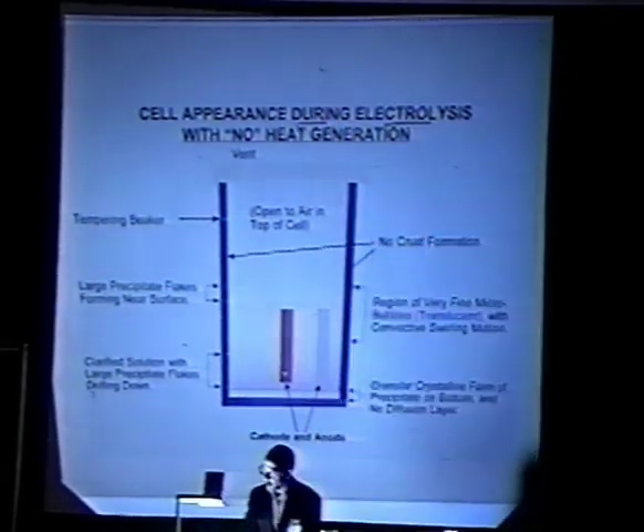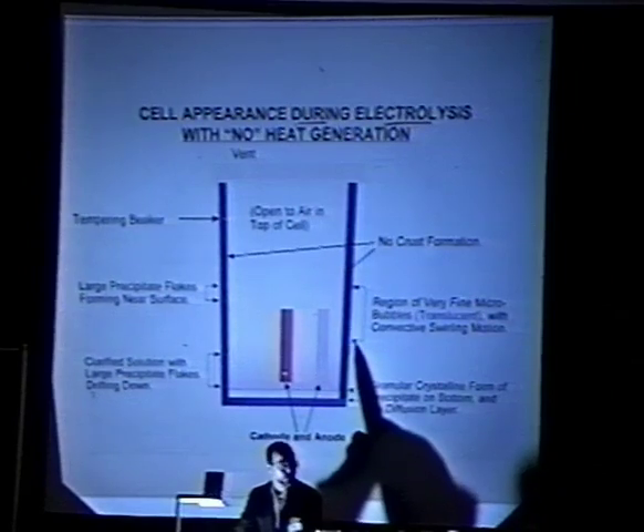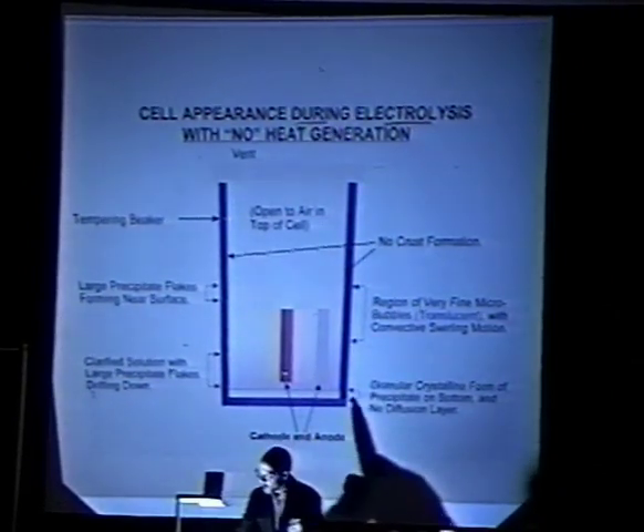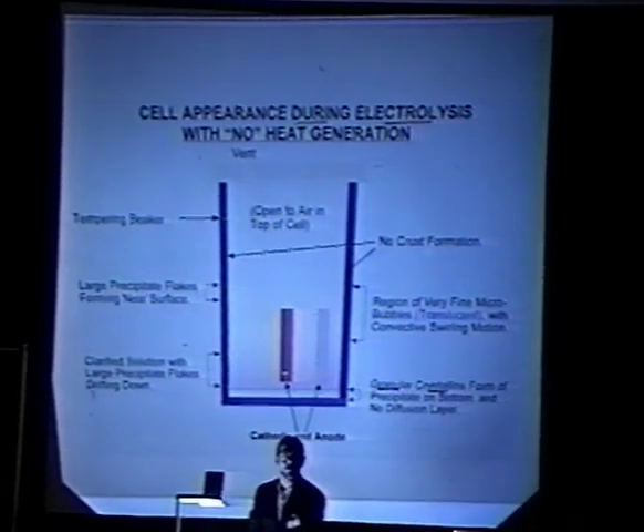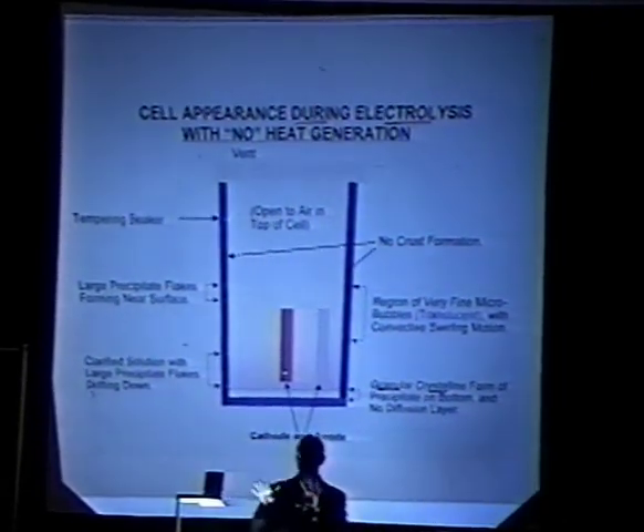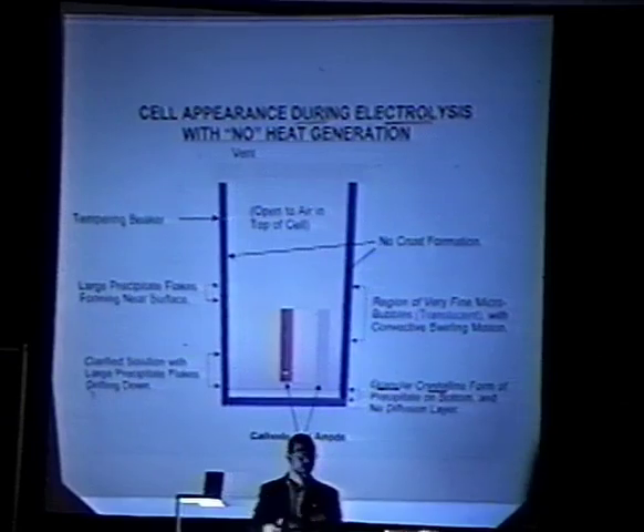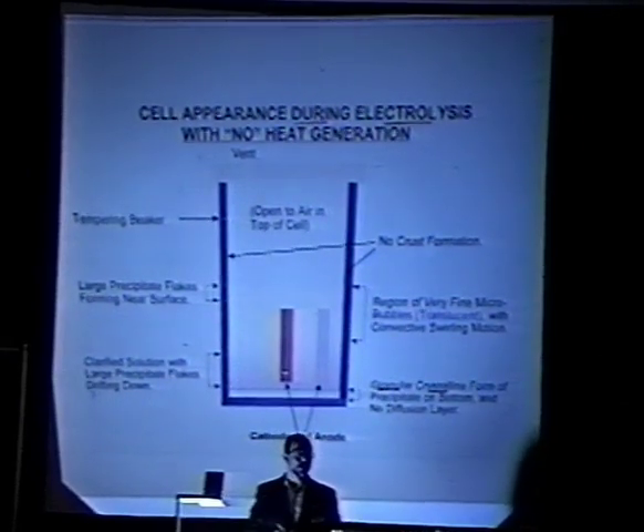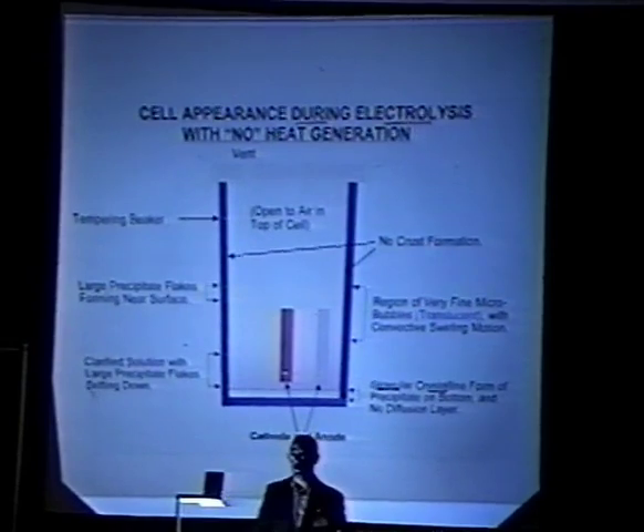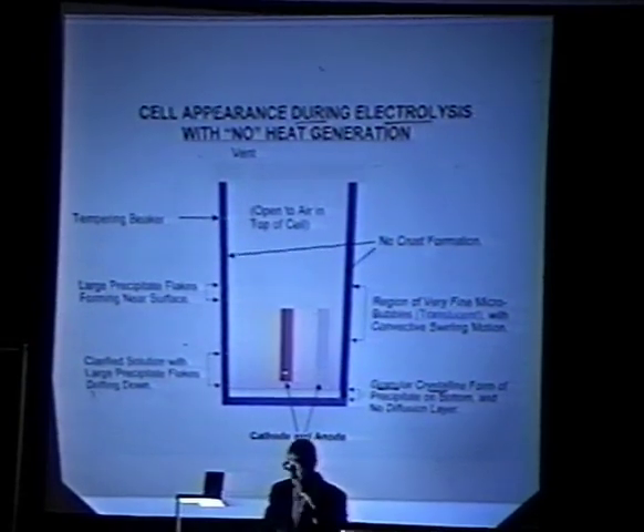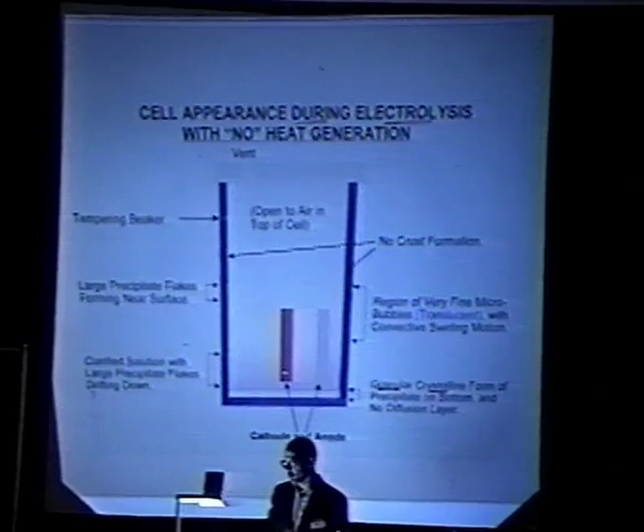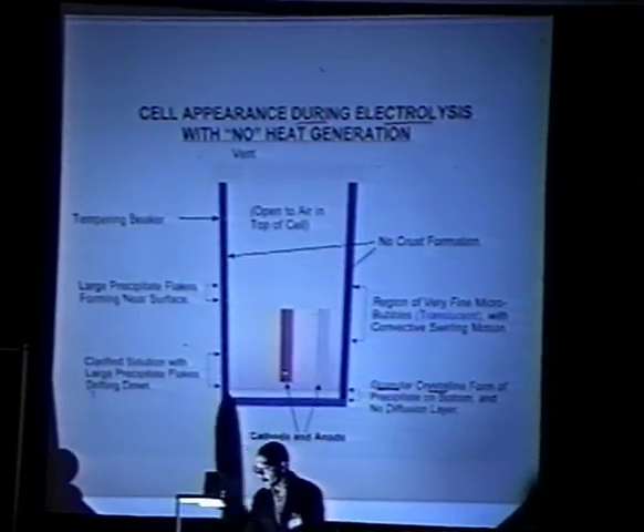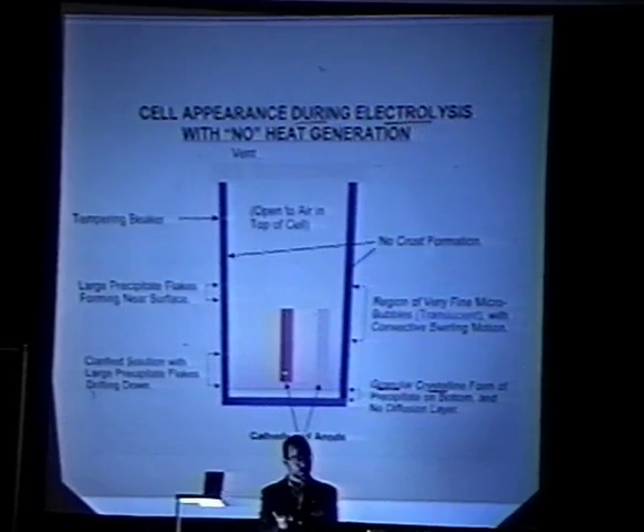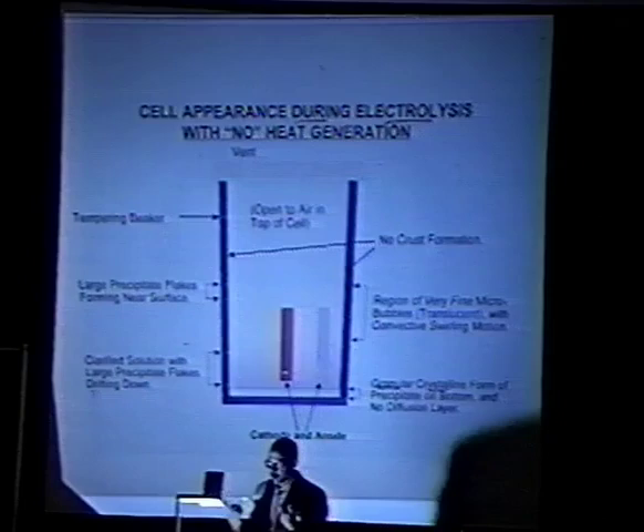Again, during electrolysis, you still have the region of the fine microbubbles generated by the electrodes. But you also get what I call a granular crystalline form. I've taken both the silty powder form and this crystalline form to the chemical lab. They've analyzed it. It's always lithium carbonate, but they look drastically different in terms of their crystal structure. Well, again, this could be a major difference. This particular material forms, and the depth of it in the bottom of the cell just grows depending on how long you run the current. But you can force the carbonate to form just by running current.